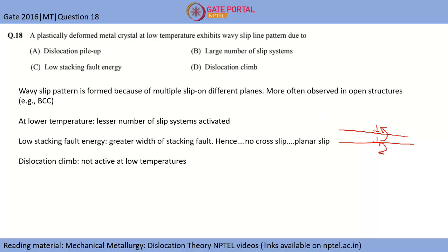Now again coming to the question, as a plastically deformed metal at low temperature, so low temperature dislocation climb is not active. Low stacking fault energy cannot lead to multiple slip on different planes because the width of the stacking fault is higher, hence no cross slip occurs, and a large number of slip systems are not activated at lower temperature. So what it does is, the dislocations which are moving on different planes try to come at the same point and form jogs, or if this dislocation is moving on this plane and on this plane one dislocation moving, these are trying to come at the same junction. So here these dislocations will pile up, and this pile up will lead to slip on some different plane. Hence this will give dislocation pile up and later wavy slip.